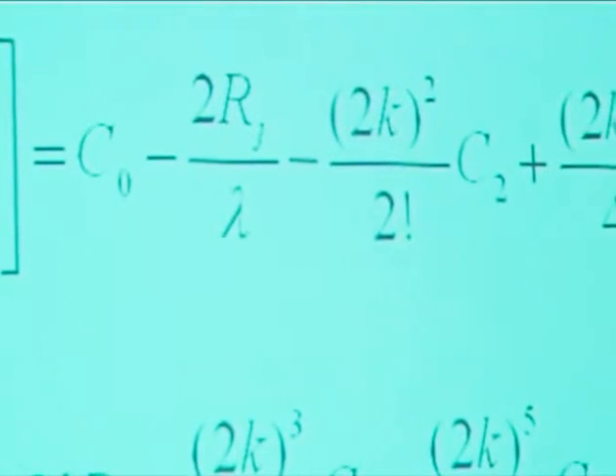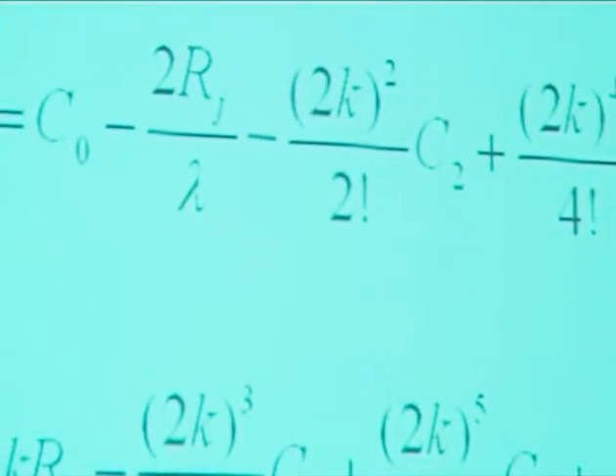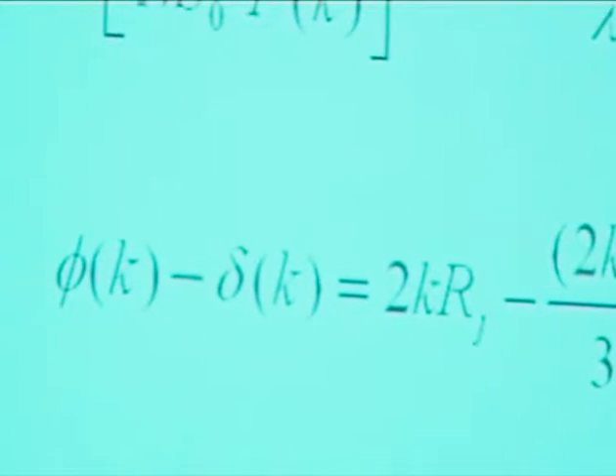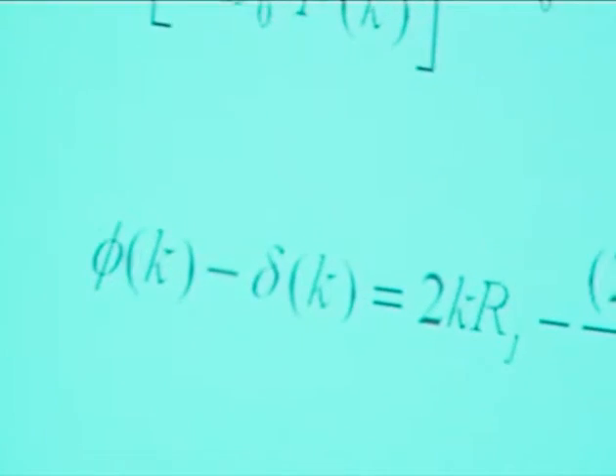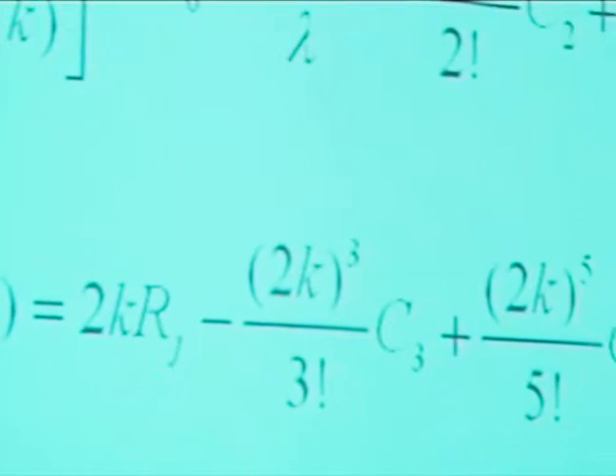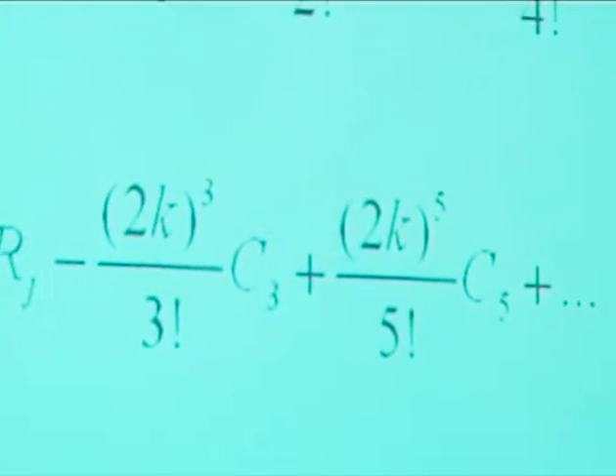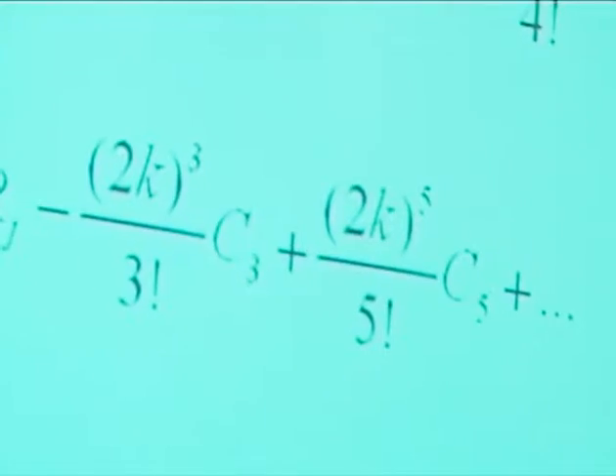If it's Gaussian, it's the classic analysis. If it's a distorted Gaussian, I'm in trouble. And actually that's what I had in this MoS2 particle. I had a distorted Gaussian, because most of my distances were 3.16, but those at the edge were shorter. So I have a skewed distribution. And the way to handle that is to come up with a skewed distribution and put it in here, do the analysis, and then you get two factors out.